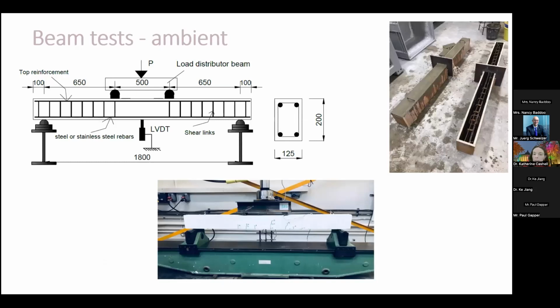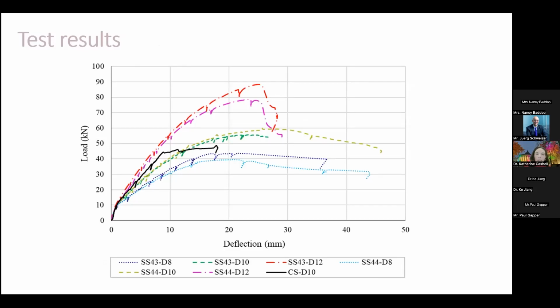We've also done some beam tests, looking at the development of cracking and things like that, and different reinforcement ratios and cover distances. Generally, as you would expect, what we have found is just a lot more ductility, and failure does not occur at such an early stage for a stainless steel reinforced concrete member.